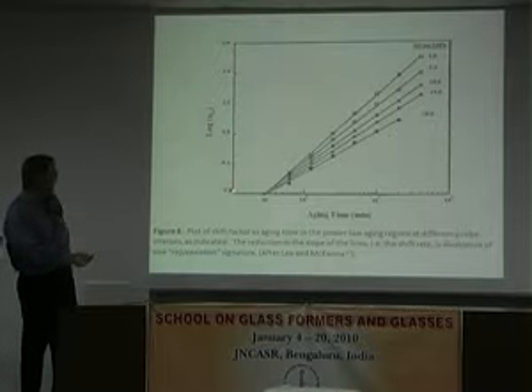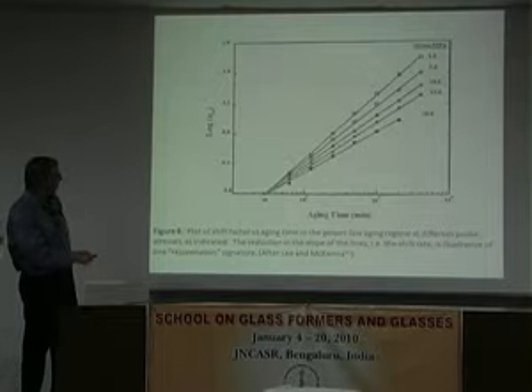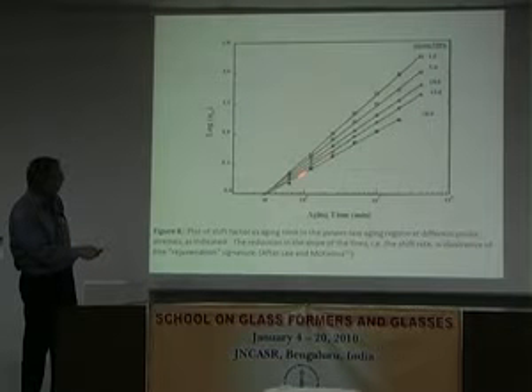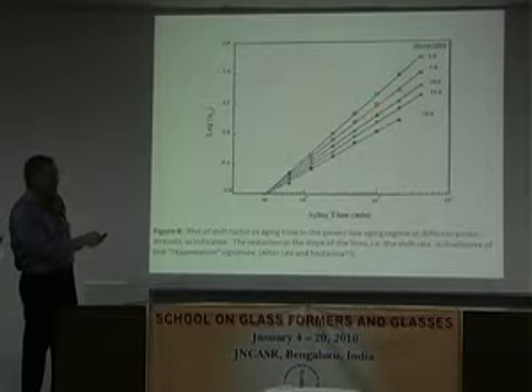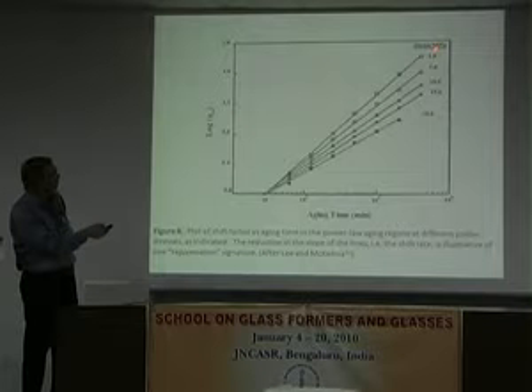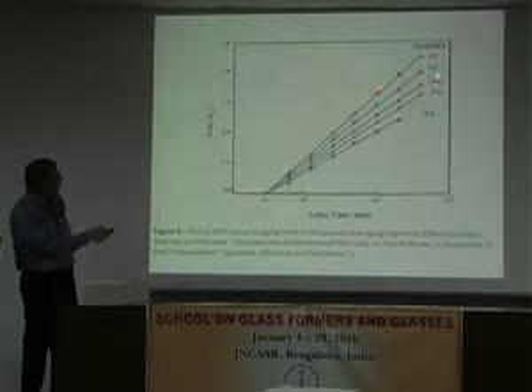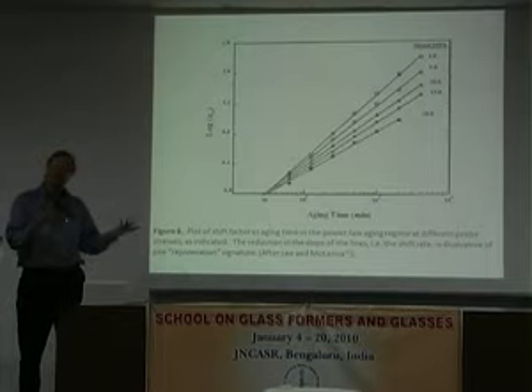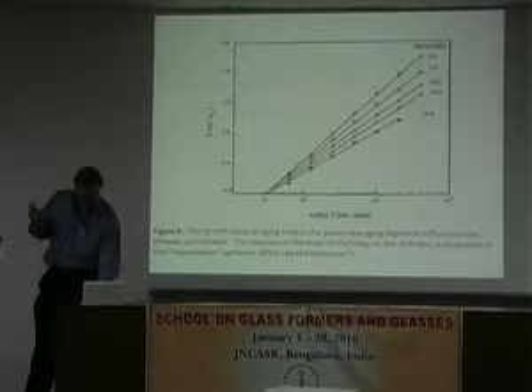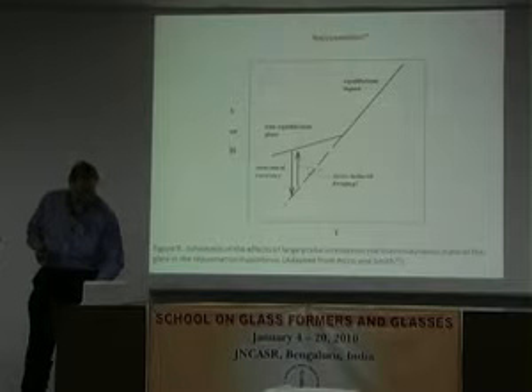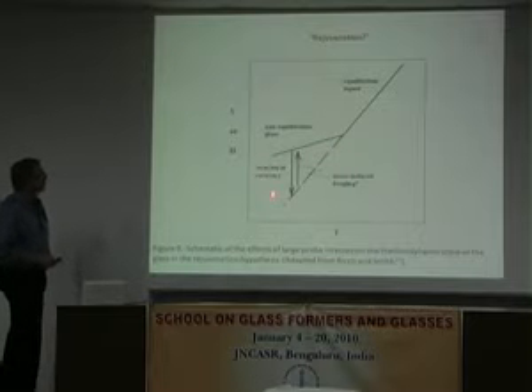So again, this is a log of the shift factor versus aging time, again in this down jump sort of power law regime. And you see that the slope, or the shift rate, gets smaller as I increase the stress. That's a so-called signature of rejuvenation, and this was one of the hypotheses for what happens.